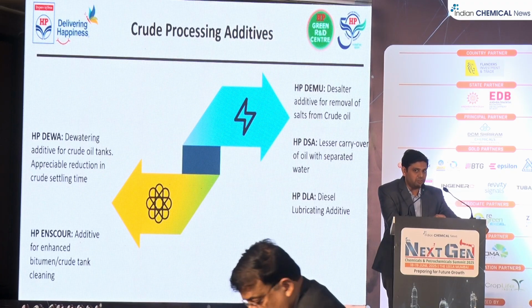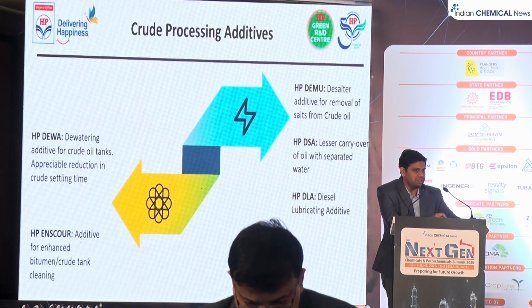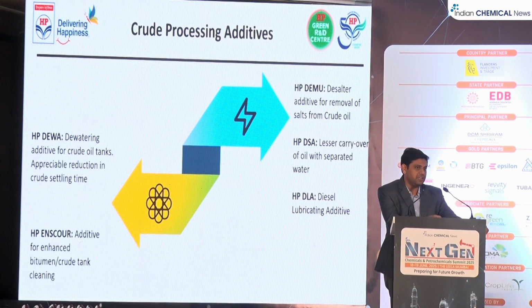So HP Dewa is a dewatering chemical that is used in crude oil tanks. We have seen that generally after buying the crude, we keep it for 12 to 16 hours for settling the water. Now, after applying the chemical, we reduce the time to 6 to 8 hours. So we can process more crude by using the chemical.